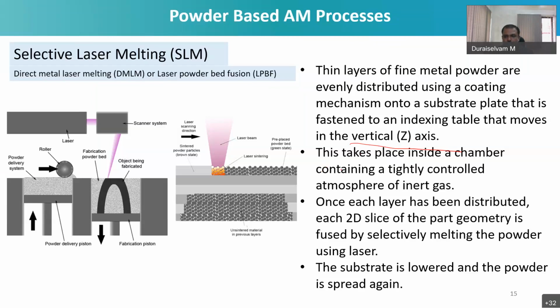product. So once each layer has been distributed, each 2D slice of the part geometry is fused by selectively melting the powder using a laser. Basically, these 3D printing systems cover only a 2D area in the X and Y direction. And since you are lowering one by one and fusing the powder in the Z direction, finally you can realize the entire component in a 3-dimensional pattern.